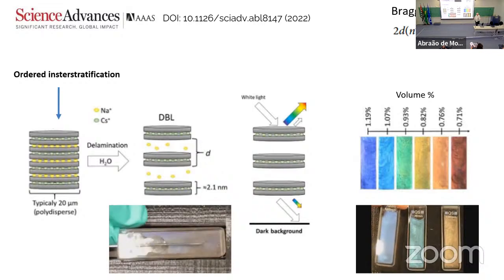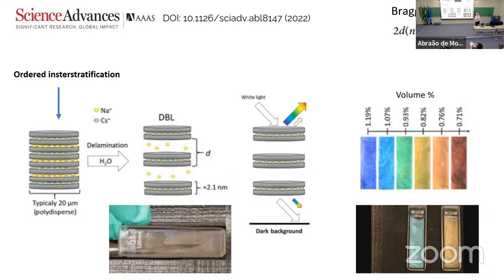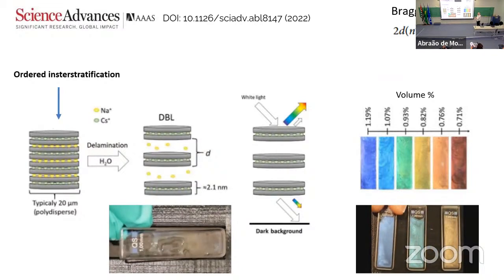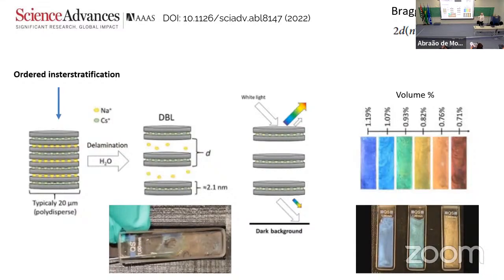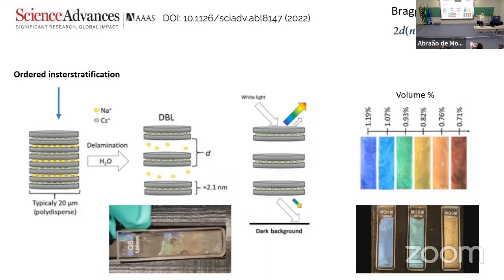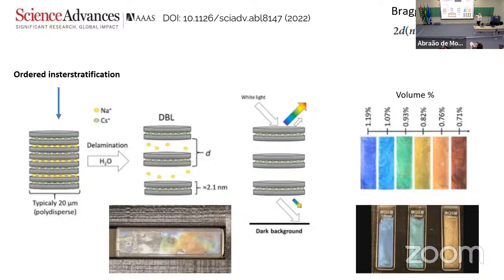Now, a single sheet of graphene is almost fully transparent. So with the single sheets of clay, fully transparent, you shine white light on them, and the light goes straight through. These ones have a partial mirror effect. So you get something reflected, and it's enough to get very nice interference and colors that will vary just by volume percent of clay platelets in the suspension, which controls this distance between them.